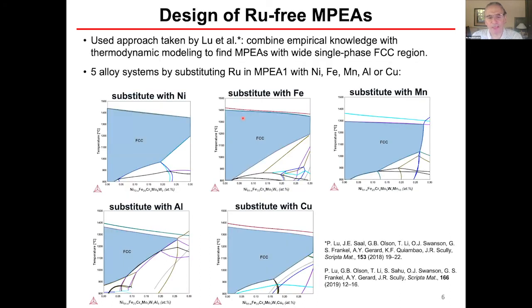So the approach that we've taken is, again, not unlike what we've heard from the other speakers, but we started with our MPEA1 and substituting in elements. These 5 elements are the usual suspects of the commodity elements that would go in. And we use Thermo-Calc to then look for what alloys in particular would have these ranges. Here were these wide compositional single phase ranges we're interested in to be able to solutionize. Okay, and so you can see, I'll show you the compositions we ended up with, but each of them has such a wide range. And you'll note that at lower temperatures, all kinds of phases are predicted to form by Thermo-Calc.